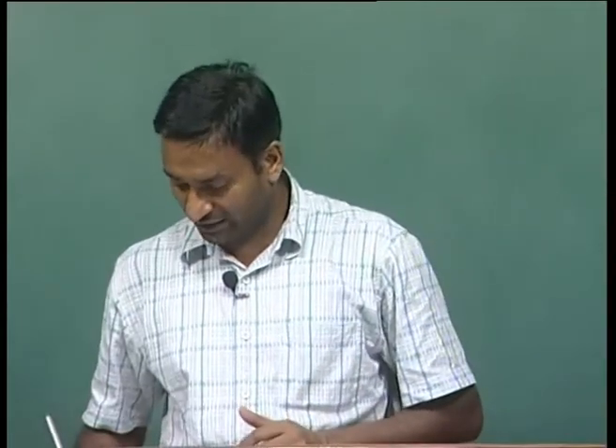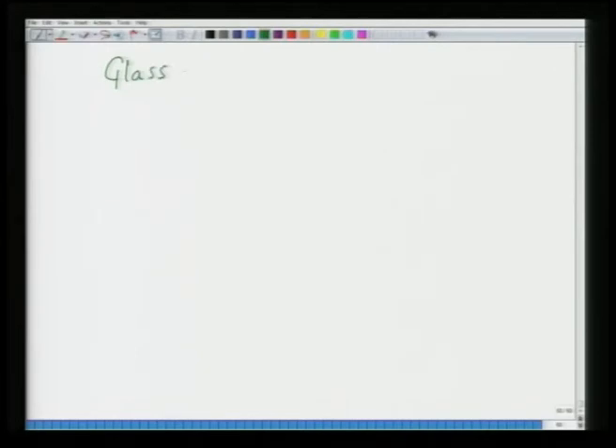In conducting ceramics there are two categories: glasses (including molten silicates) and fast ion conductors. Glasses do not have a periodic arrangement of ions — they are amorphous. Unlike crystalline materials they have no specific melting point; rather they have a softening point where viscosity decreases until they become fluid.